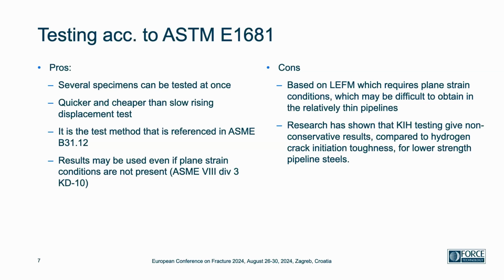And one paragraph in Division 3 KD-10 says that the results may even be used if plane strain conditions are not present. But we'll come back to that. That's as long as the test specimen is at least 85% of the final thickness of the pipeline.